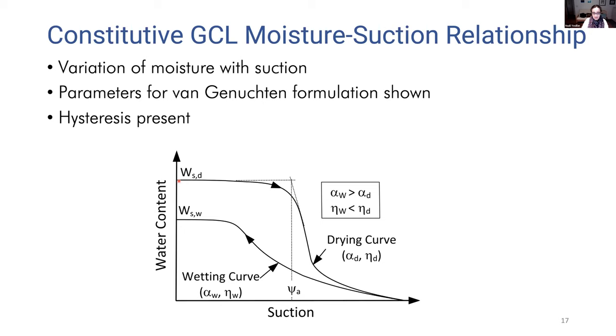And another significant component of the moisture-suction relationships is that there is hysteresis in the system. The drying desaturation curve is different than the wetting curve or saturation curve, hydration curve. And the difference between these two curves results mostly from geometric constraints, including inability to overcome some larger pores when the material is wetting as opposed to going through drying, as well as differences in contact angle between the soil surfaces and the wetting fluid along the wetting and drying paths. The differences are more pronounced at high degrees of saturation or high water contents at relatively low suction values, and the two curves actually start getting pretty close as the suction increases and moisture content decreases, reaching a single curve in the end at very high suction values.